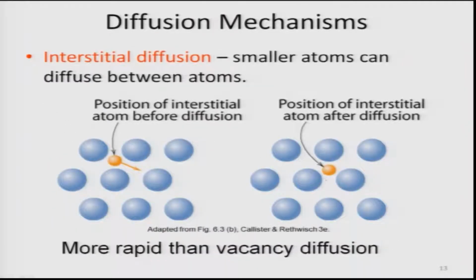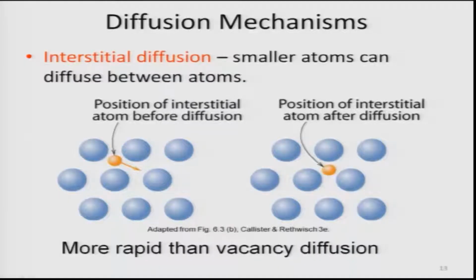Many situations are possible. But a similar situation is not true when you have interstitial atoms like carbon in steel, or boron in a nickel aluminum alloy. The atomic size is very small, so they will be sitting in the interstitial positions. Interstitial position means in between the lattice positions there will be interstitial positions like octahedral voids and tetrahedral voids. I already told you, again taken from Callister.